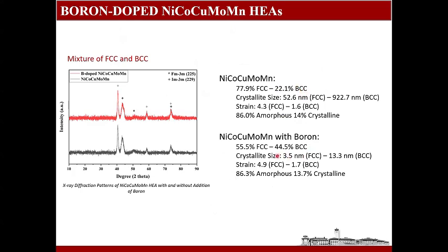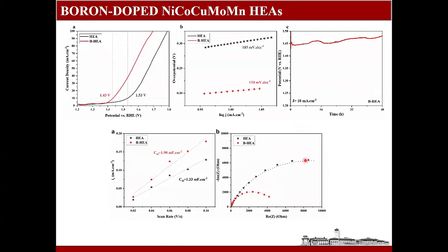So these are again obtained from the Rietveld analysis of the X-ray diffraction pattern. The introduction of the boron decreased the crystallite size, from 52.6 nanometers to 3.5 nanometers for the FCC, and from 900 nanometers to 13.3 nanometers for the BCC. And it also increased the strain a little bit, as you see, for both the FCC structure and the BCC structure, which is expected and the desired property.